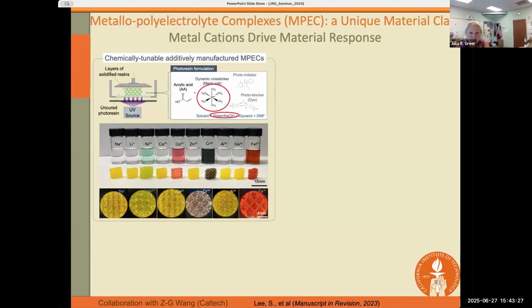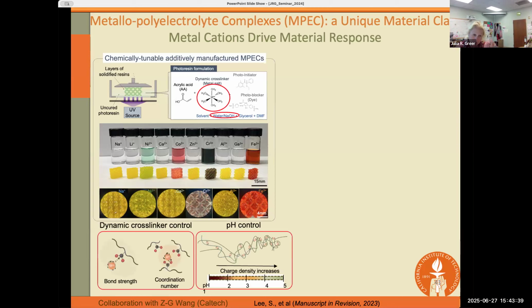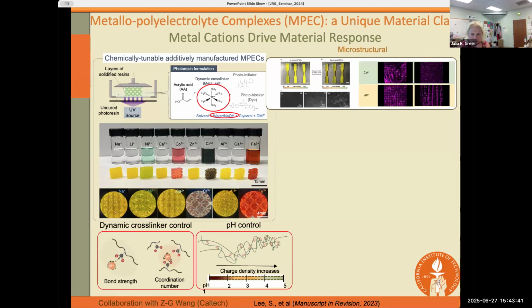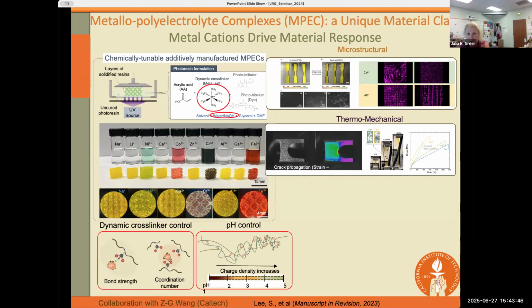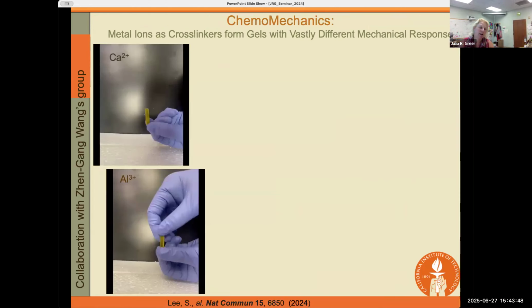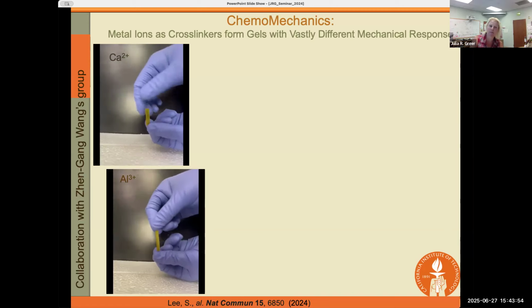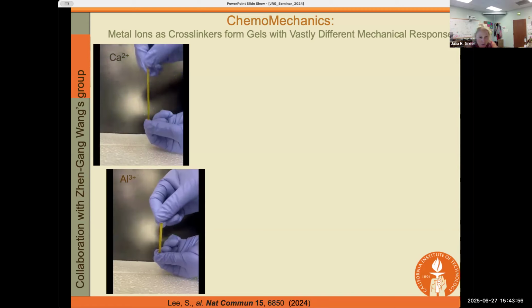Instead, she utilized this concept of dynamic cross-linking, where the bonds that are formed between the metal ion and the polymer backbone are non-covalent. And so the formation and the dissociation of these bonds, as well as the local pH environment, gives this very intimate coupling between chemistry and the mechanics of these materials. And I'm going to show you these two videos. So the one on top is infused with calcium, which is a divalent metal, of course, and the one on the bottom is infused with aluminum, which is a trivalent metal.